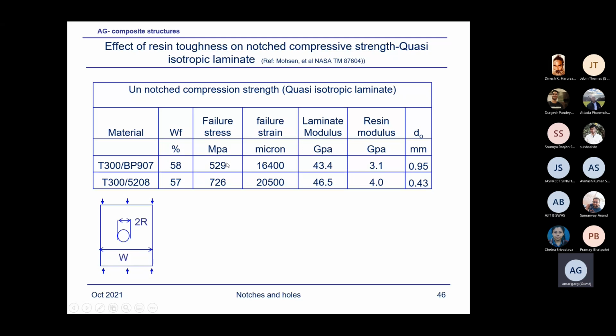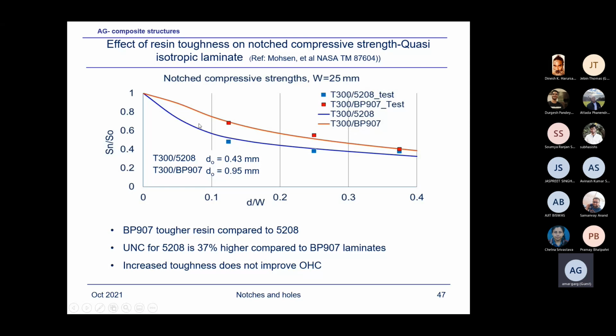So failure stress 529 MPa and 726 failure strain, and as you can see here, resin modulus 3.1 and 4. For this, I plotted from the test data of this Moisen. Again, this is from NASA. And this is for toughened one, sigma N by sigma naught. And this is for the brittle material.